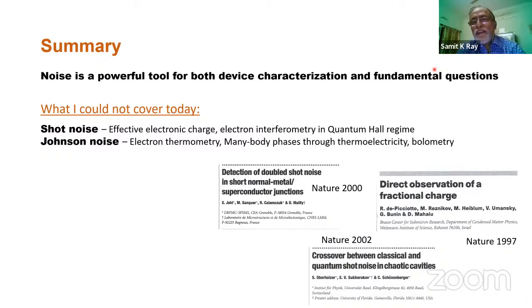Yeah, right. So please continue. If you've got a perfectly crystalline system, the only noise that can come is from the environment. So first you clean up the crystallinity of the sample, and then you screen it from the environment, and that gives you the lowest noise device that you can make.